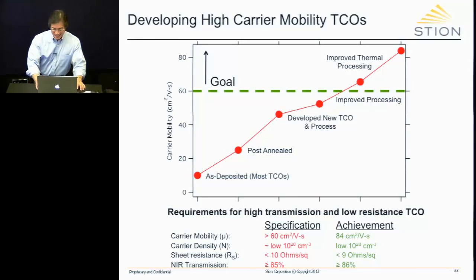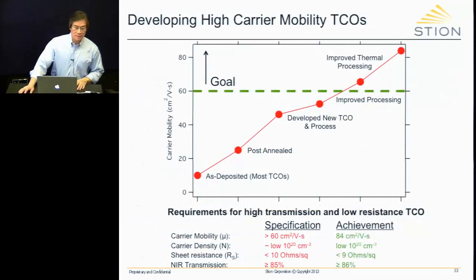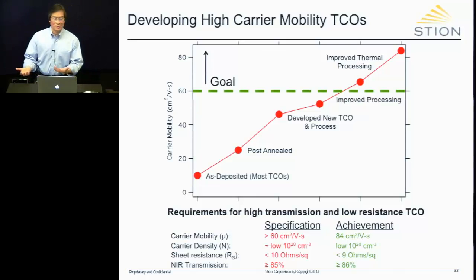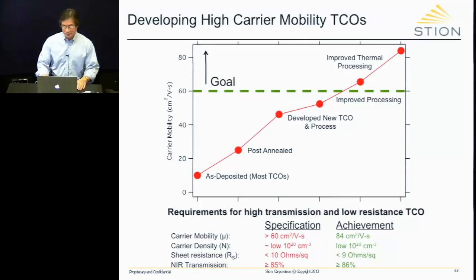Thank you. Where does indium oxide fit in again? Indium oxide actually, by itself, would get higher mobility in general than zinc oxide-based materials. But ITO by itself does not do it for you. And the other problem is that indium oxide has a different lattice structure than zinc oxide, and that's part of the reason behind it. But the other problem is that it has indium. We already use a lot of indium already, and so there's an issue with the cost. We've been able to negotiate long-term contracts to bring that down for us. That's a good question.